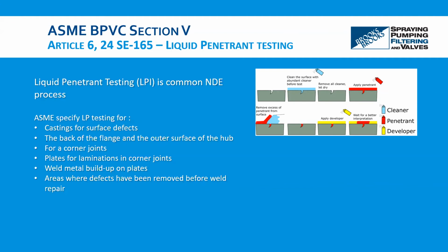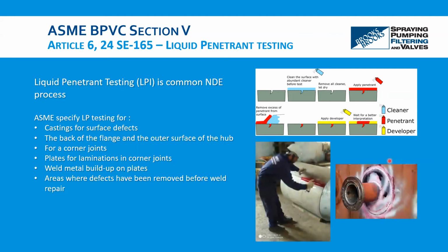Once the surface is prepared, we can then apply the penetrant, this here, and then through capillary forces, it penetrates, hence the name penetrant, into these surface imperfections. Then once the surface is cleaned of the excess penetrant, a developer is applied, which over time will change in color, as you can see here, as red.